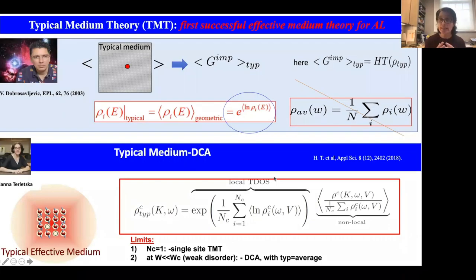So to incorporate these ideas into the effective medium approach and modify the CPA approximation, Vlado Dobrosavljević, my PhD advisor, pioneered the so-called typical medium approach. And the idea is that once you calculate your disorder-averaged Green's function in your self-consistency loop, he suggested that instead of calculating the linearly averaged Green's function, you calculate the geometrically averaged Green's function, which is an approximation for the typical or most probable value that one would like to study.